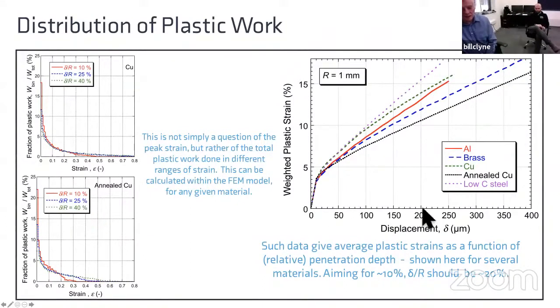So this is 20% penetration. And as you can see, if you go to that kind of depth, you're generating average plastic strains that are affecting the behavior up around 10 or 15%. And that should be suitable for capturing the behavior overall. Do need to go reasonably deep. So say 20% is a typical value we aim for.